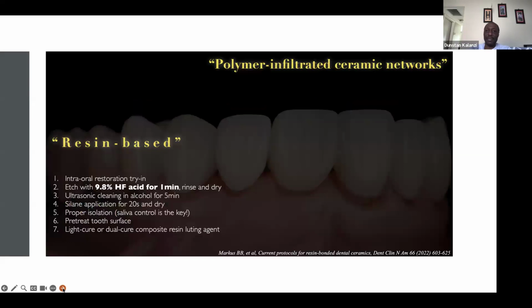For the polymer infiltrated ceramic networks, you still do the same. You do 9.8% hydrofluoric acid, you do the silane application, you pre-treat the tooth surface, and then you light cure or dual cure composite.